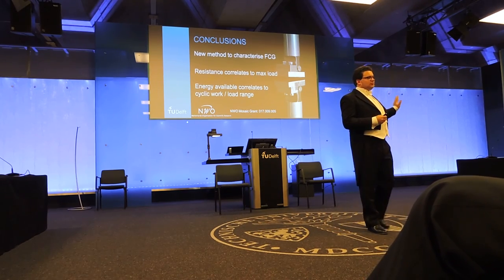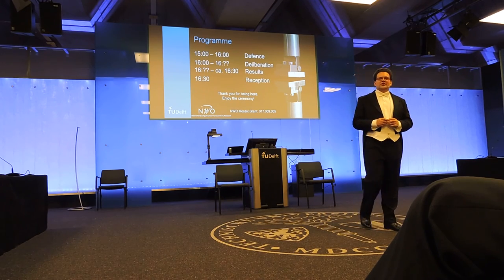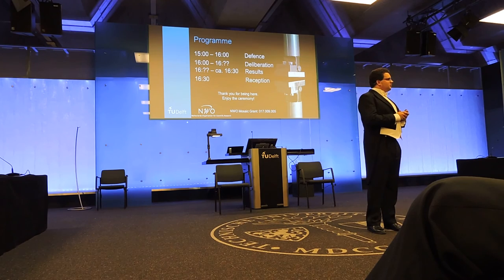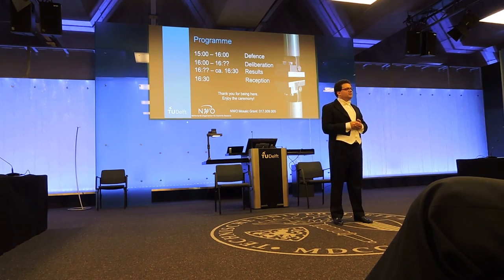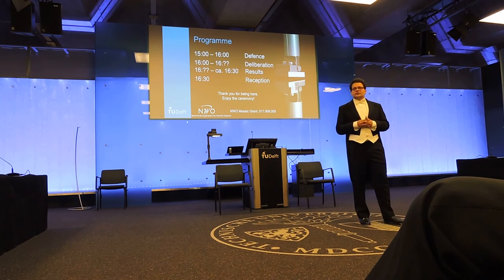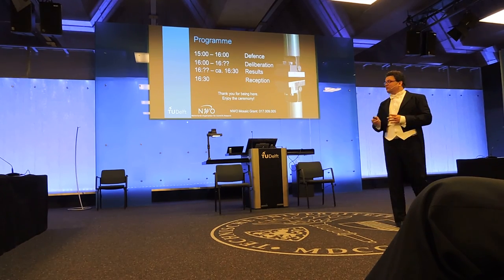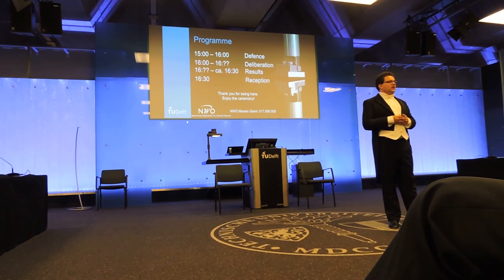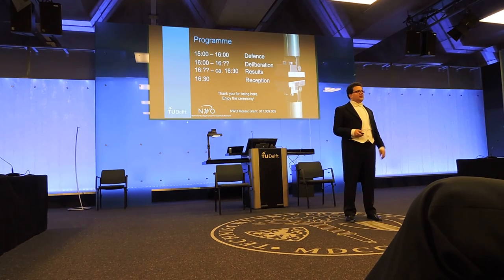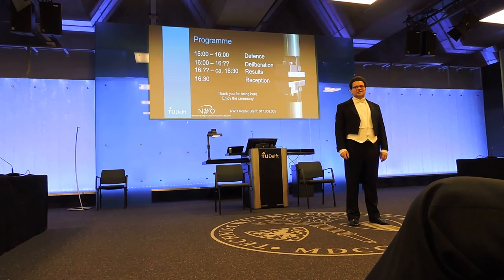So what should you remember from my thesis? Three things. First, I found a new method of characterizing fatigue crack growth by measuring the energy dissipation and using that as a new way of looking at the problem. Number two, I found that how much energy we need to generate a certain amount of crack growth seems to depend on the maximum load we're applying, and how much energy we have available seems to depend on the range of the load, or on the cyclic work applied. Those are the key points of my thesis. For those of you who don't attend defenses often: at exactly three o'clock the committee will go in — one chairman and seven other members — who will ask me questions about my work for exactly one hour. The committee will then deliberate, decide whether to award me a diploma, and come back around twenty past four. After a brief ceremony, hopefully they'll give me a diploma. Then at 4:30 there will be a reception where you are more than welcome. Thank you all for being here — I hope you enjoy the rest of the afternoon.